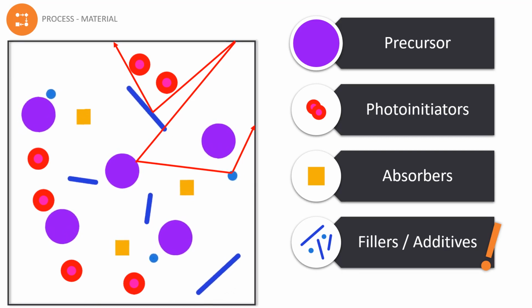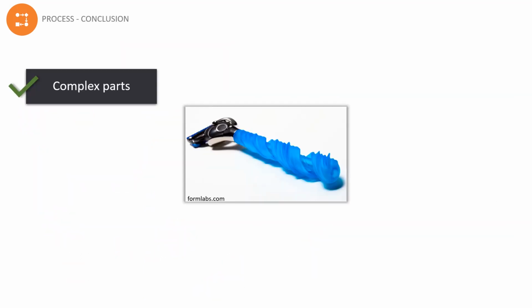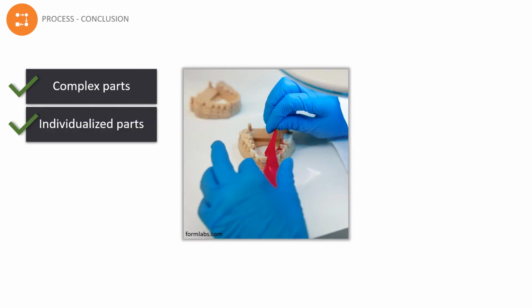As in all 3D printing techniques, part quality depends greatly on the material choice. Although for SLA there are extensive resin libraries and there is active research done on new compositions, some application areas are better suited for SLA than others. If the finished part has to fulfill high demands concerning resolution and surface finish, SLA is a great choice. Layer thicknesses of down to 10 micrometers are possible because scanning speed, laser power and Z-stepper motor of the building platform enable high control on the curing depth and therefore the vertical resolution. The lateral resolution, or curing width, is mainly influenced by the laser spot size, which can be easily controlled as well. This enables the printing of highly personalized products such as dental implants, hearing aids or other prostheses, where the geometry is highly adjusted to the patient's body.